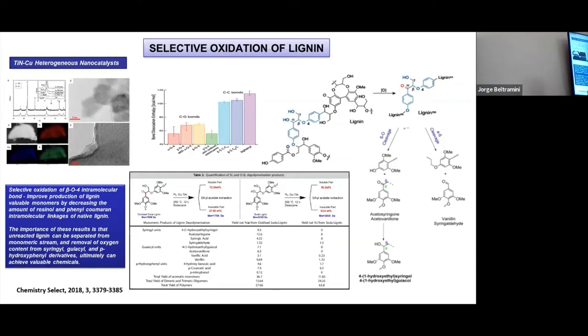And what about if, close to the beta-O4, in the position alpha, we do a selective oxidation? We oxidize that hydroxyl over there. If we do that selective oxidation with a particular catalyst, we can reduce dramatically the bond dissociation enthalpy. So the amount of energy that you need to put in to break this bond will be reduced, and the other ones will not be modified. So will we do a good cleavage? We prepare a catalyst based on titanium nitride and supported on copper. So using this catalyst, we have the right functionality in order to attack that bond.